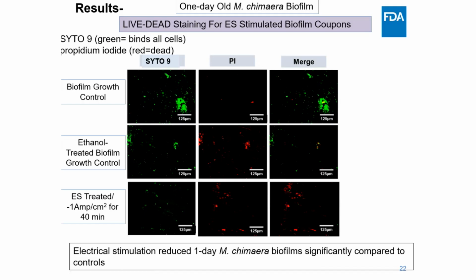So to further confirm our finding, we use fluorescence microscopy to visualize biofilms after electrical stimulation, applying live/dead staining to the stainless steel coupon after the stimulation. In this method, we are using two fluorescence dyes, SYTO 9 and propidium iodide. SYTO 9 penetrates all bacteria and stains them green. Propidium iodide only enters bacteria with damaged membranes and stains them red. When used together, this dual stain approach allows us to distinguish live from dead cells in the biofilm.